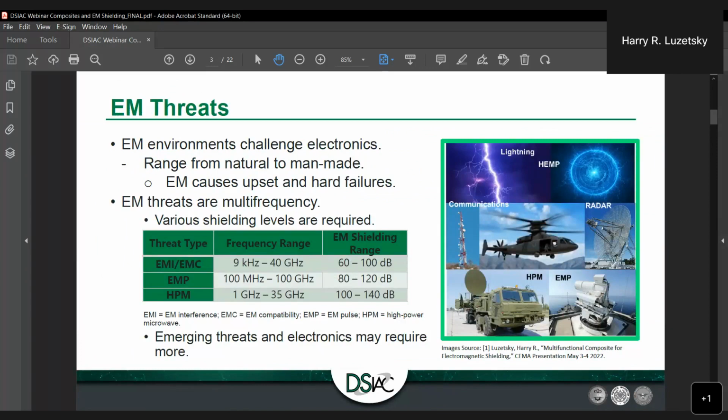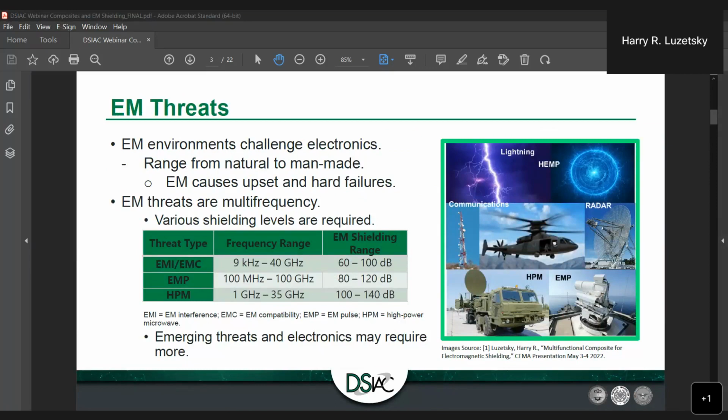So with a lot of these other materials, what we're seeing is you're only getting around 60, 70, and even somewhere upwards of 80 dB. And at this point, I surmise that most of that has to do with you're just not getting the contact between those materials.